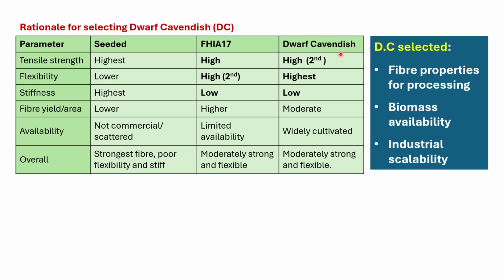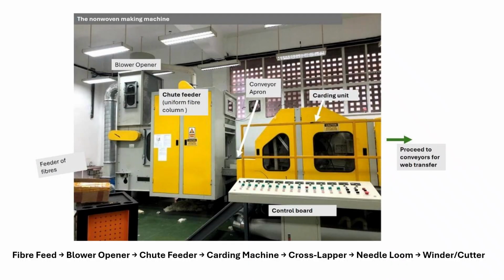So Dwarf Cavendish was retained for the mat making, because it satisfied several criteria: high tensile strength, highest flexibility, low stiffness, and also it is widely cultivated on the island. So this will ensure a regular supply of the raw material. Now, to make the mat, the needle punching non-woven processing technique was adopted, as you can see here.